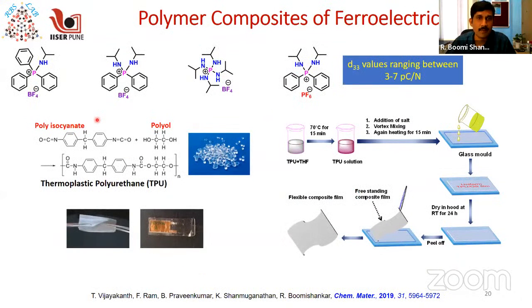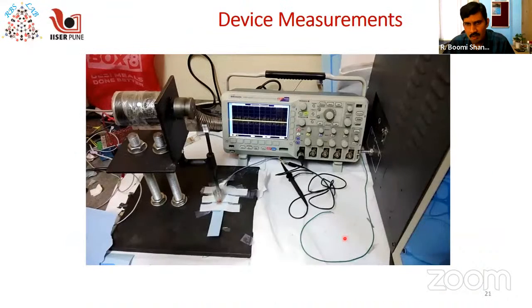And then subsequently, we made a polymer composite. In this instance, we used a TPU polymer instead of a PDMS polymer. This is the typical procedure with which you can make a polymer composite, which is mixing the solutions of the polymer and your compound, dissolving it, and then pouring it onto a glass mold, allowing the crystallites to grow into the polymer, and then you can take the polymer composite out for your measurements, by peeling off. Now these composites can be placed between two aluminum contacts or copper contacts, and then you can subject them to mechanical energy harvesting application.